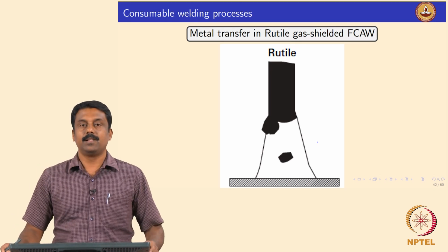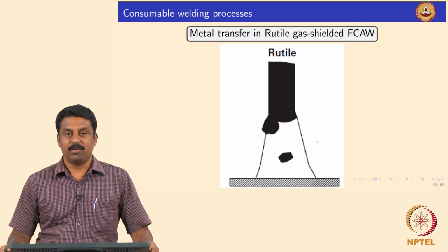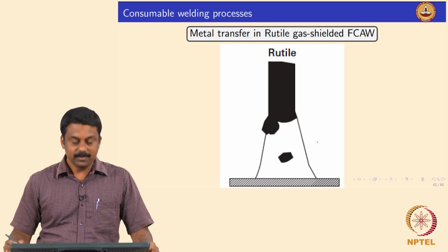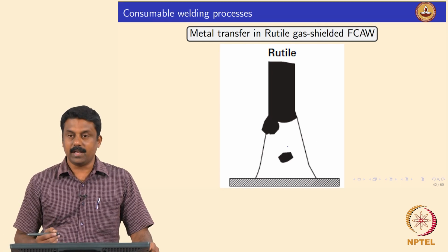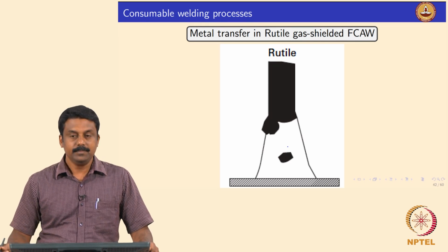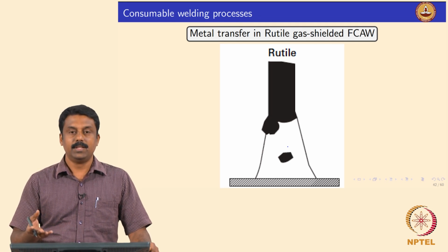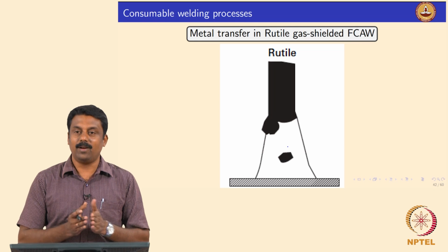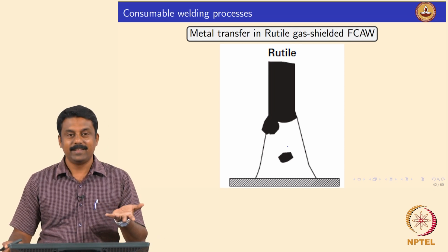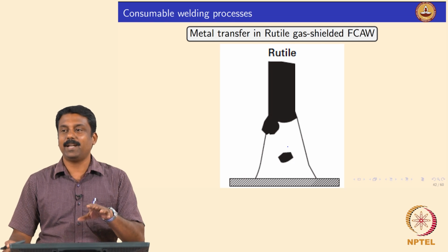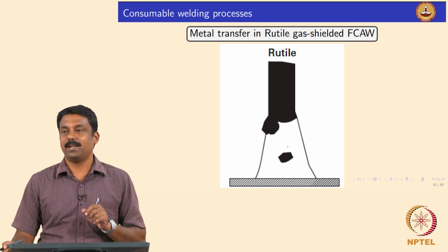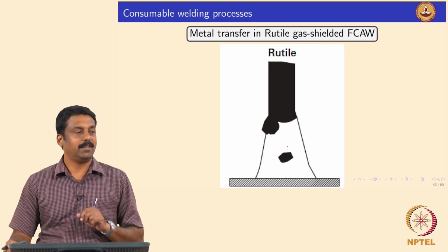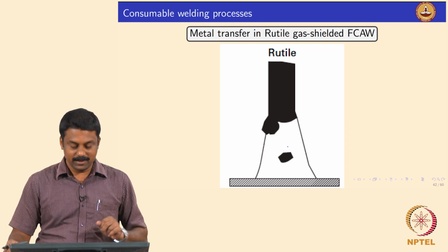So, this is a similar, say, simple schematic given by Professor John Norrish in this book. Where a rutile electrode promotes the droplet transfer characteristic with much smaller diameter by influencing the surface tension. The video I showed you, that is not a rutile electrode, that is a self shielded electrode, where the droplet is not transferred at all. I mean, even after keeping for a longer time, the droplet is still intact. Okay. So, by just adding some titanium oxide, we can promote the droplet transfer much more effectively by changing the surface tension, right. It is clear.